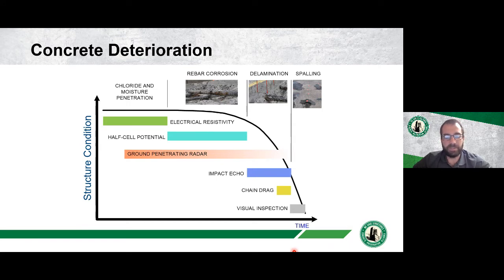So if we go out and look at a structure and we find a delamination, well, there are other areas of that structure that are probably rebar corroding without delaminations. There's probably areas that have some chloride and moisture exposure that haven't started to corrode. So all these conditions are happening simultaneously on a structure. So if we just identify where the delaminations are, are we really understanding the true condition of the structure? And are we really rehabbing it or extending its service life in an effective way if we don't understand where those other conditions are?